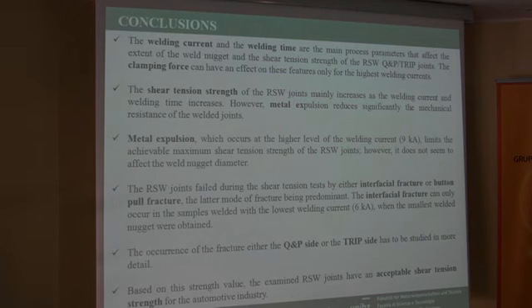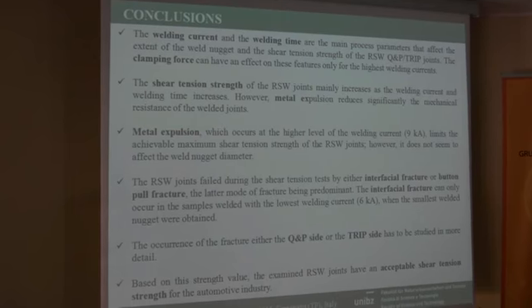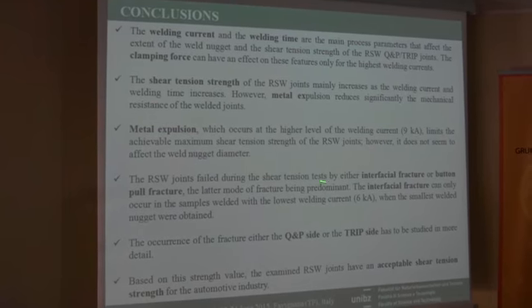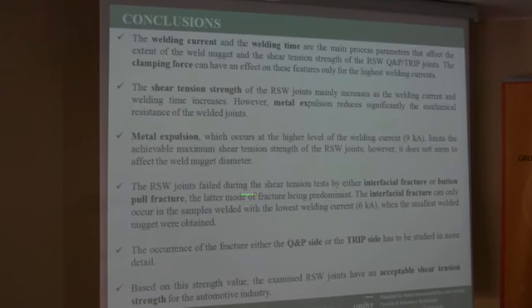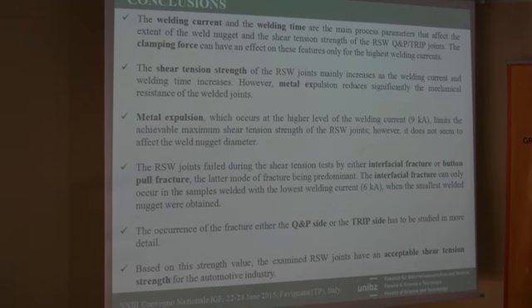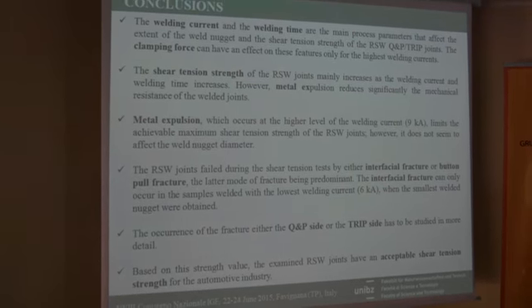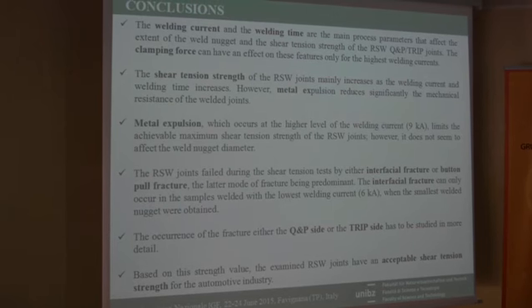So there are some conclusions, but you can have a look. In particular, here you can see the effect of welding current, welding time, and the mechanical strength. Obviously, increasing this value, you can increase the mechanical strength. You can see that the metal expulsion reduces significantly the mechanical resistance of the welded joints. You can also consider that we have some interfacial fracture and button pullout fracture according to the side of the button pullout, and according to the process parameters.